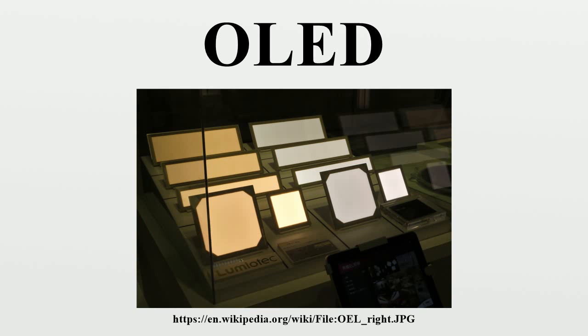Metals such as barium and calcium are often used for the cathode as they have low work functions which promote injection of electrons into the LUMO of the organic layer. Such metals are reactive, so they require a capping layer of aluminium to avoid degradation.